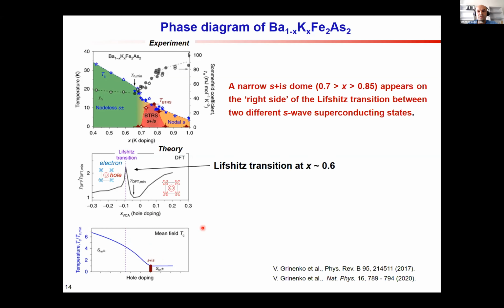So now I would like to conclude. We found the presumably S+is state in the narrow doping range between 70 and 85% of potassium doping, on the right side of the Lifshitz transition. And here I would like to emphasize that the Lifshitz transition plays an important role in changing the pairing interaction in the system, and gives the possibility to have these very exotic superconducting states with broken time reversal symmetry. So thank you for your attention.